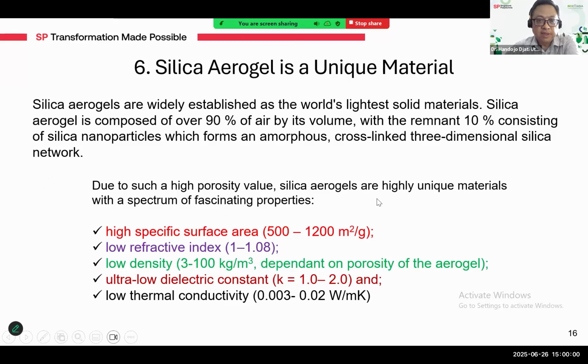As mentioned by Dr. Lee before, this is considered the world's lightest solid material, composed of about 90% air by volume and 10% silica nanoparticles in the form of an amorphous cross-linked three-dimensional silica network. Because of the high porosity, silica aerogel has unique characteristics. We have a high specific surface area, up to 1,200 square meters per gram. We have a low refractive index, 1 to 1.08, and low density.